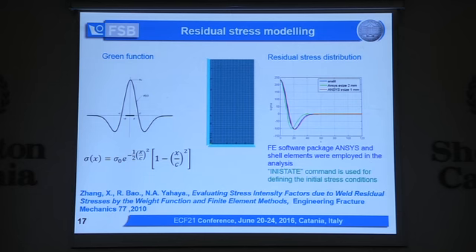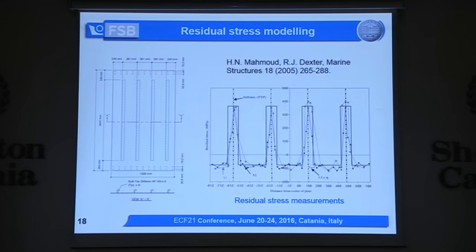introduce residual stresses into our finite element model by using ANSYS and INISTATE command. And for that a certain fine mesh is needed, and with 1 millimeter element size, we could do this successfully. And this is what other authors measured who are concerned with crack propagation and residual stresses in deck structure of a ship. So they measured residual stresses and they obtained, you see, this was measured, and they tried to idealize this with such rectangular distribution.